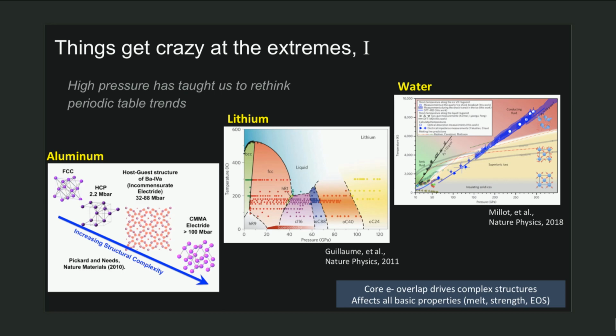I never imagined that I would be working in a field where the science that we're being told about sounds a little bit like science fiction. What's crazy is that we used to think that matter got simpler with pressure. As you squeeze metals, they become more close-packed. But what has been found in the past 10 years or so is that as you go to higher and higher compression, the symmetry doesn't become just close-packed and simple, but we actually have really complex structures. And this is because, as I mentioned before, we have participation of the core electrons in addition to just the valence electrons. And so there isn't enough space for our typical bonding rules to control.